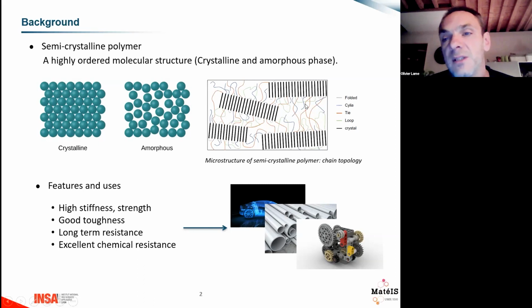And here is the complexity of this kind of material, because in this amorphous phase, the question is its ability to transfer the stress between the different lamellae. And there are many kinds of chains. There are chains that are linked to crystallites, which are called tie chains. There are loops that come from a crystallite and come back to the same crystallite. There are some cilia or pendant chains that go from a crystallite, and the chain end is in the middle of the amorphous phase. All these kinds of chains should play a role in the mechanical properties, and we have to perform simulations to be able to understand that.